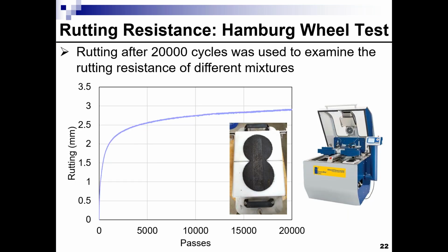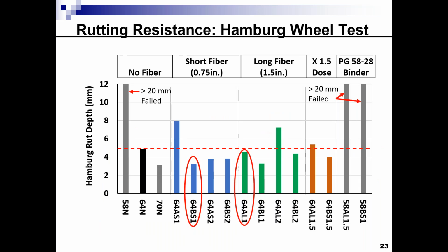In terms of the rutting, we use the Hamburg. The main parameter that I will be showing is really the rutting after 20,000. This is basically the rutting in millimeter. Our criteria is basically if it is higher than 20 millimeter, then we consider the sample to be failed. Again, we're seeing that the Aramid fiber improved the rutting.